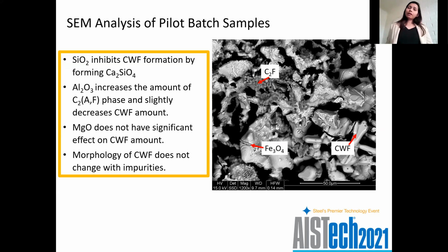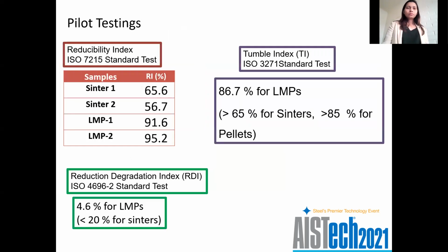We found the same results with the pilot batch as well. The magnetite concentrate had about 4.98 percent silica and about 1.5 alumina, so we saw this C2F and Larnite phase as well. We can't see them in these SEM micrographs because these are just broken samples, not polished. But you can clearly see this CWF phase still has this beautiful platelet shaped morphology. So the samples were indurated at 1050 for 2 hours, 8.5:1 ratio. We created a huge lot of them for these pilot testings.